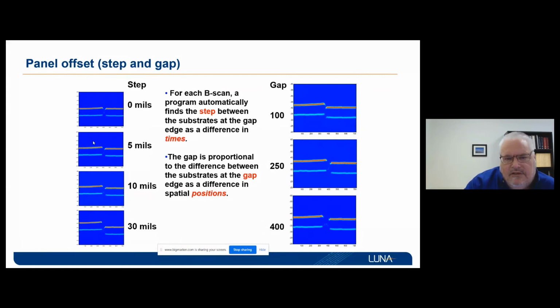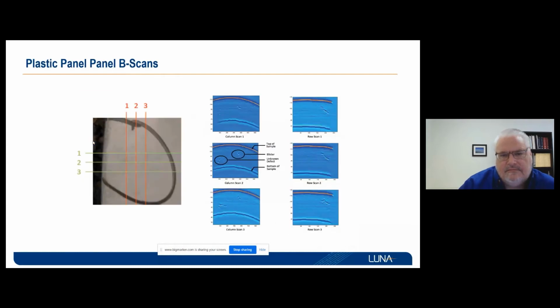One of the applications that we developed was measuring the panel step offsets between two panels that had coatings or boots applied to them. And of course, the coating and boots could be slightly different on both sides. So if you wanted to align the thickness of the underlying outer mold line of the panels, you could use this to measure the step and gap offset of the panels to adjust them into correct tolerance.